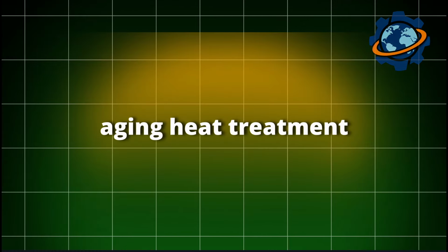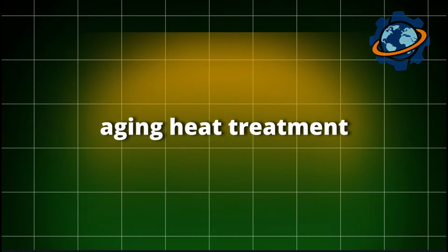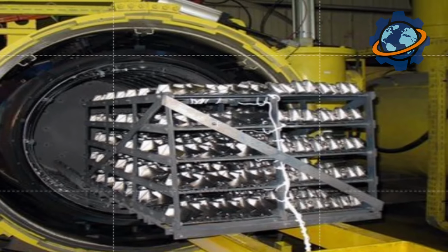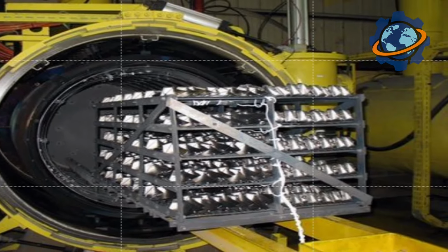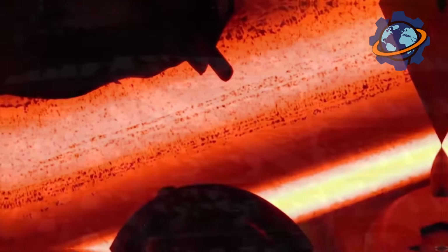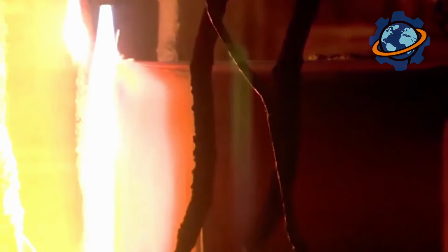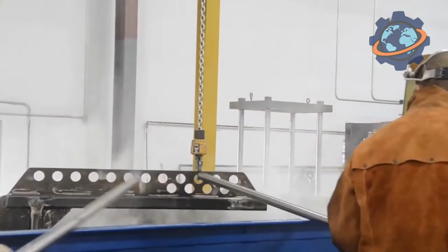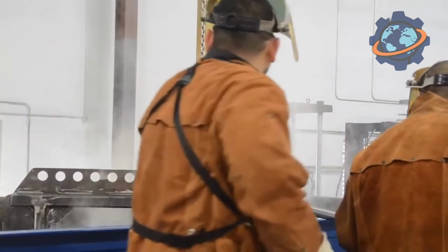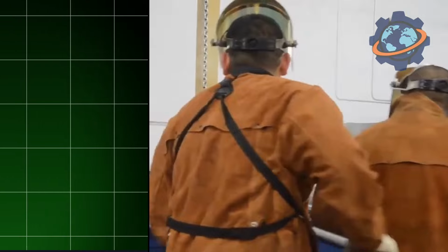This locks crystal structure permanently and precipitates microscopic strengthening phases throughout the lattice. Next comes aging heat treatment, multiple cycles at precisely controlled temperatures that cause nanoscale particles to form. These particles, called gamma-prime precipitates, occupy 70% of the alloy's volume. Picture this: imagine a 3-dimensional checkerboard where hard particles pin the crystal lattice, preventing atoms from sliding.